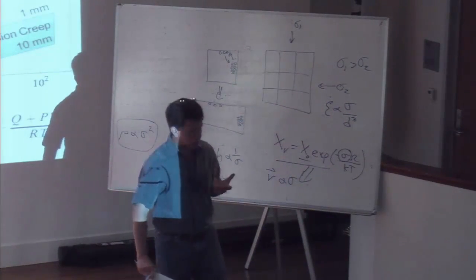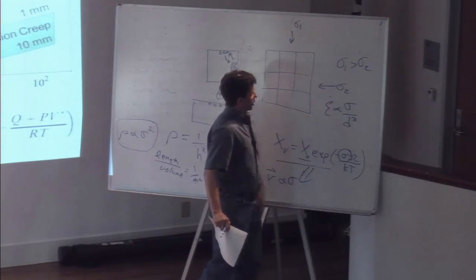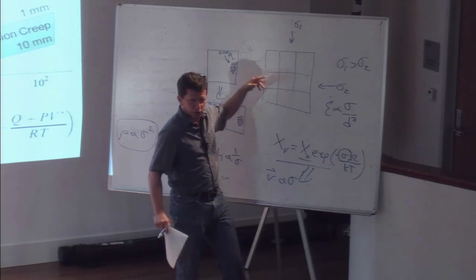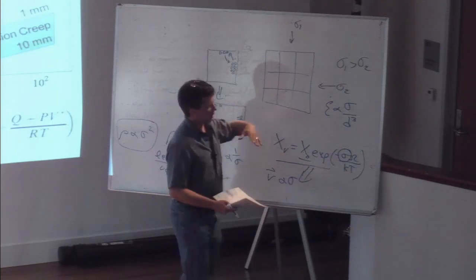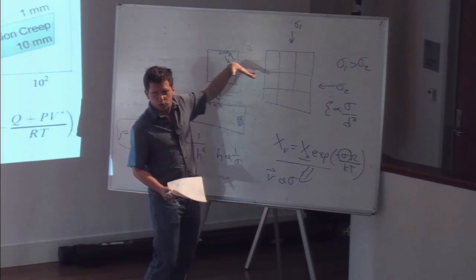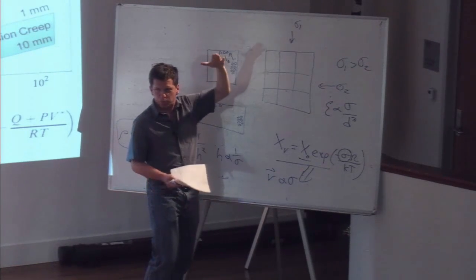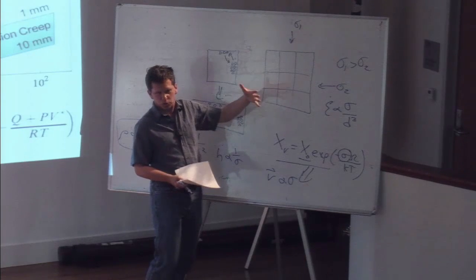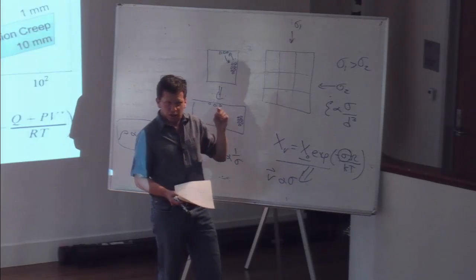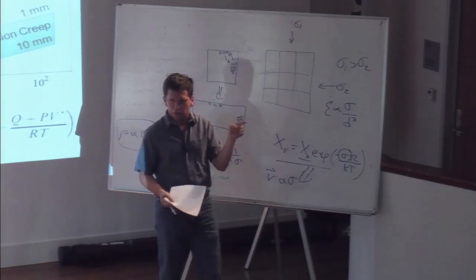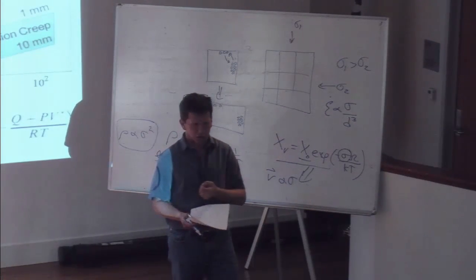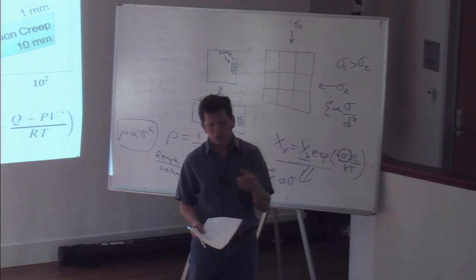Okay? So really quickly, one of the grain sizes comes from the length scale over which the diffusion is occurring. The other is just a simple way of saying the diffusion is causing a displacement rate of the crystal. To turn that into a strain rate, you just divide it by the grain size. So you get a displacement rate divided by a grain size, and that gives you a strain rate. And the last grain size comes from the fact that the flux is limited by diffusion along the grain boundaries, and therefore there's another size dependence, which is the thickness of the grain boundary relative to the grain size.